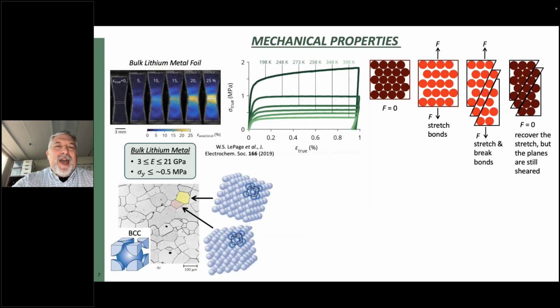And so here we go. This is now what the uniaxial stress strain curve looks like for bulk metallic lithium, and it's given to us as a function of temperature, right? Now, it turns out that lithium is highly anisotropic. So the elastic modulus, as you can see here, actually ranges from about 3 to 21 GPa, depending on the crystallographic orientation of the individual grains that make up the bulk metal, all right? And so, as you can see at room temperature and above, so that's these three curves here, right? The yield stress for bulk metallic lithium comes in at about 0.5 MPa or less, right? And so physically, that's telling us that we could pretty easily cut lithium metal with just a kitchen knife, all right?